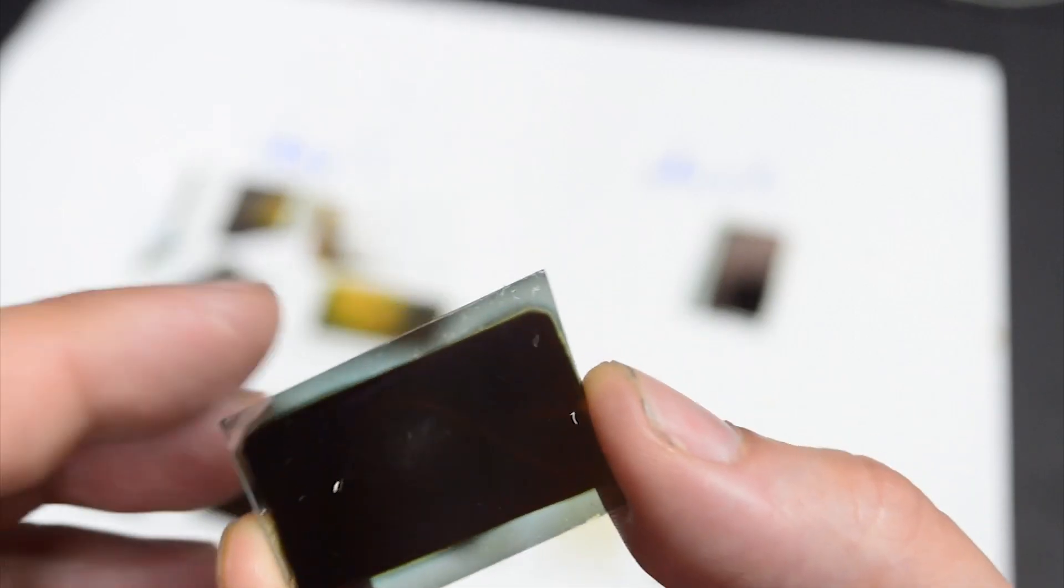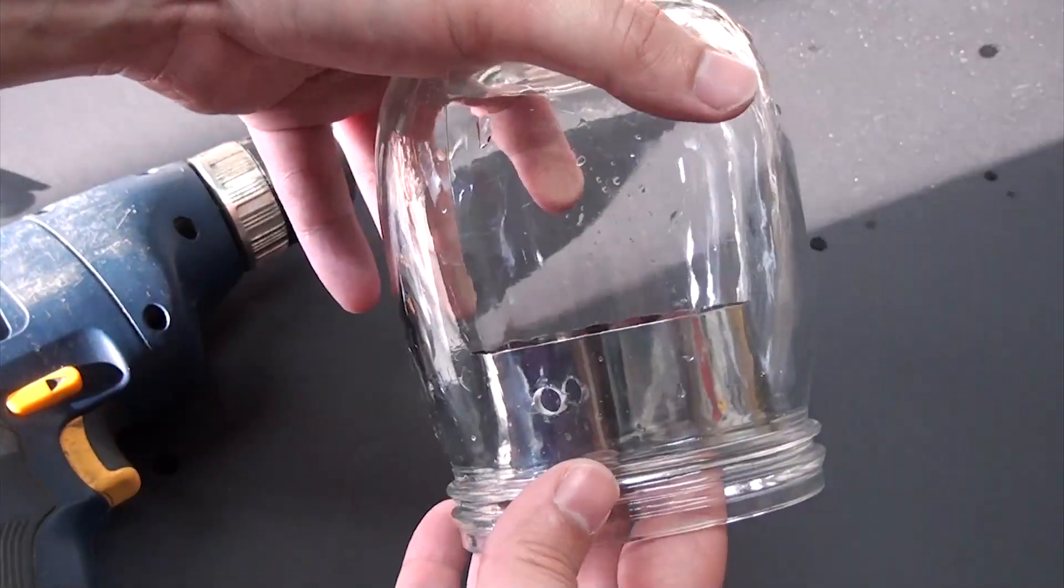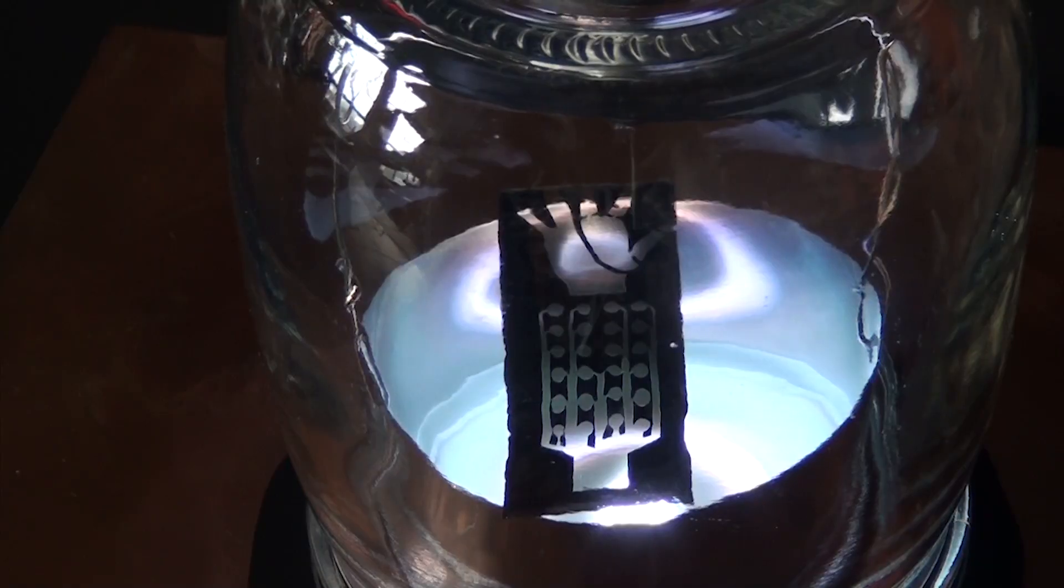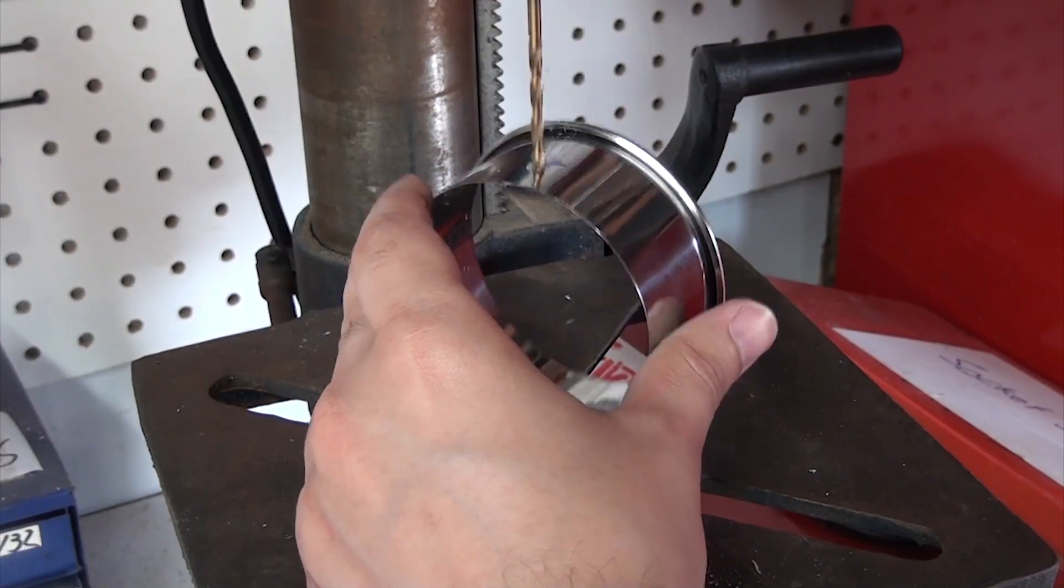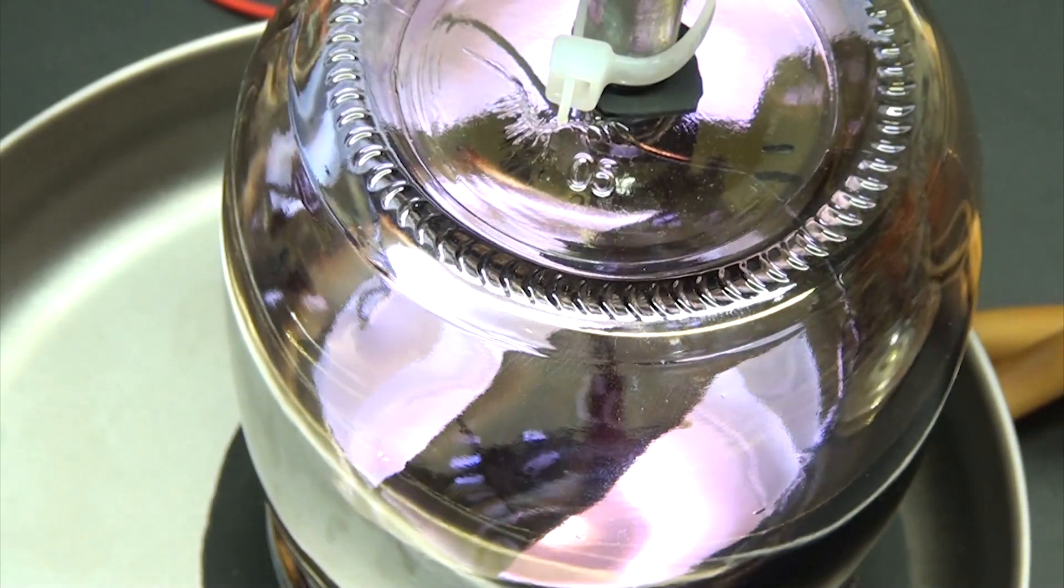First, the mild steel would get hot and start to evaporate a bit, which left a weird green haze on the glass. Second, it wasn't really as close to the base plate as it should be. And third, it wasn't stainless steel, which is a much better material for this as it doesn't have the same volatility issues. So now the anode is made from a stainless steel cookie cutter I picked up, and it's hung off the feed through using stainless steel wire.